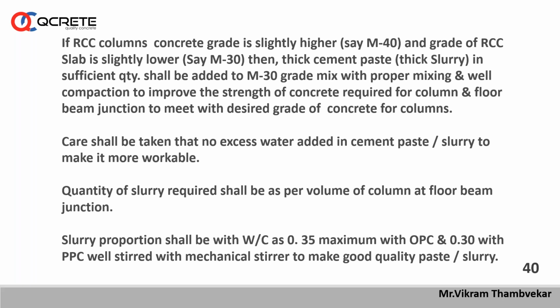Quantity of slurry required shall be as per volume of column at floor beam junction at that particular level. Slurry proportion shall be with water cement ratio not more than 0.35 with OPC and 0.30 with PPC. You have to use a lower water cement ratio for PPC and up to 0.35 water cement ratio for OPC. All the slurry should be very well stirred with a mechanical stirrer to make a good quality of paste to add in your fresh concrete.